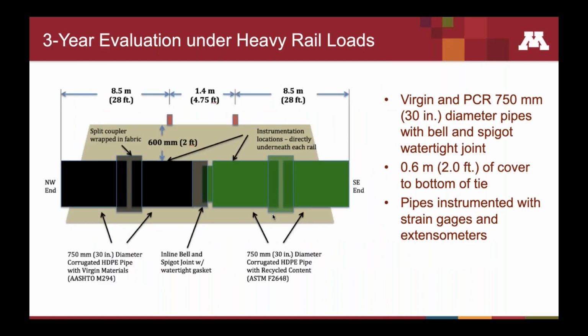The final part of the presentation I want to discuss is a 3-year study we did with the pipes underneath railroads. And now these pipes have actually been in service for 6 years. And I'm just formulating a follow-up paper on the performance of these pipes after 6 years of service. But this was an interesting application because we wanted to see how well these pipes would perform in an actual application where it was very highly loaded. So we picked a railroad application, as the rail loads are typically higher than highway loads. And we went even beyond that, did a very aggressive rail application where we only had 2 feet of cover from the top of the pipe to the bottom of the railroad tracks.